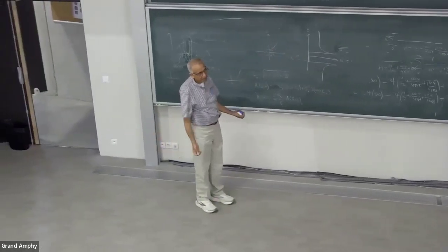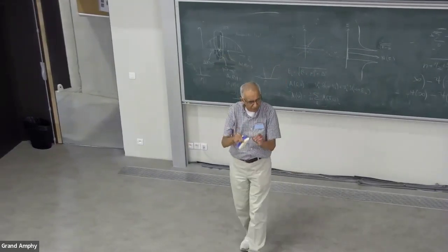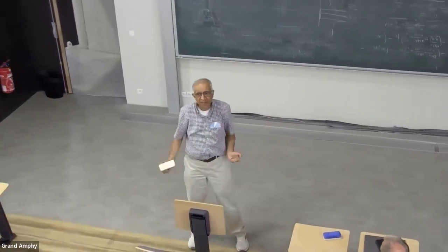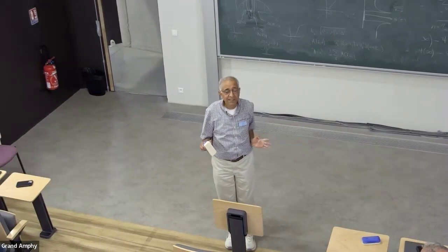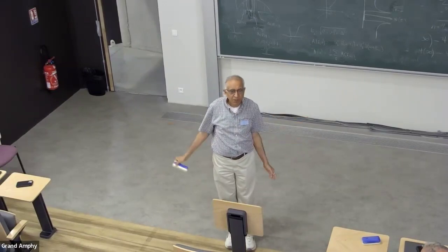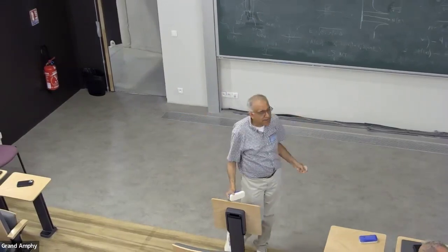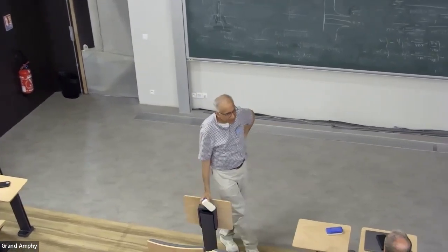Is it really a Van Hove? Many states correspond to that energy because you've made a flat dispersion there. So it's a Van Hove singularity. But if I say that, people will kill me, because the word coherence peak is just embedded in everyone's consciousness. So they call it the coherence peak. That's it. It is what it is.